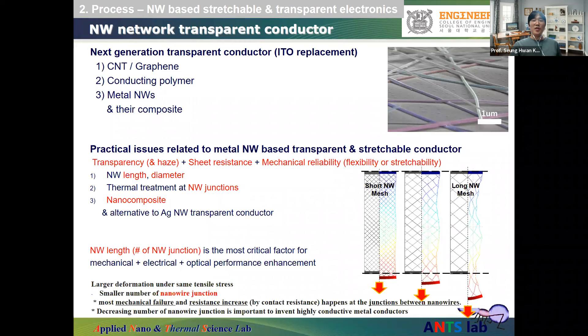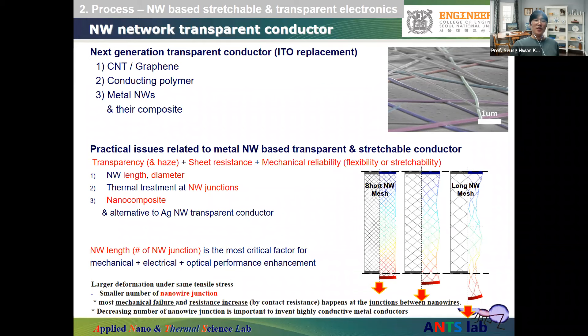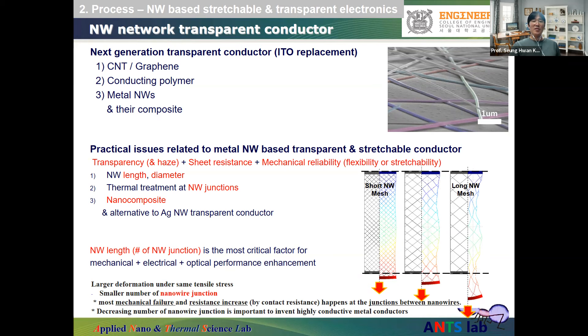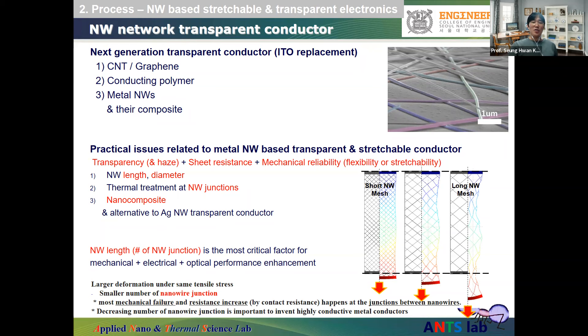Several parameters affect a highly conductive stretchable transparent electrode. Some researchers focus on developing smaller-diameter nanowires, but 15 years of experience shows that smaller-diameter nanowires can enhance transparency only, while simultaneously sacrificing electrical and mechanical properties. This is because the percolation network with longer nanowires has fewer nanowire junctions, and the number of junctions greatly influences mechanical, electrical, and optical properties. Minimizing junction count — achieved with longer nanowires — improves all properties simultaneously.